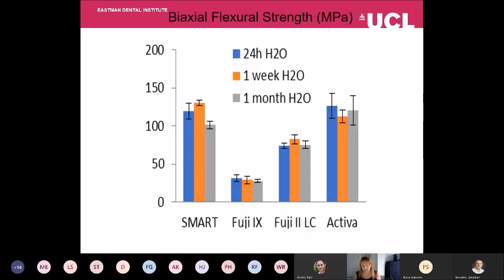If we compare smart final formulation strengths with those of commercial materials, here we've got Activa, the new bioactive composite, a resin modified GIC and a GIC. It's much stronger than the conventional GIC. It's above the 100 mark that's required for a composite, comparable with Activa, stronger than a resin modified GIC. So it's a reasonable strength. It's strong enough, particularly for restoration of children's teeth.